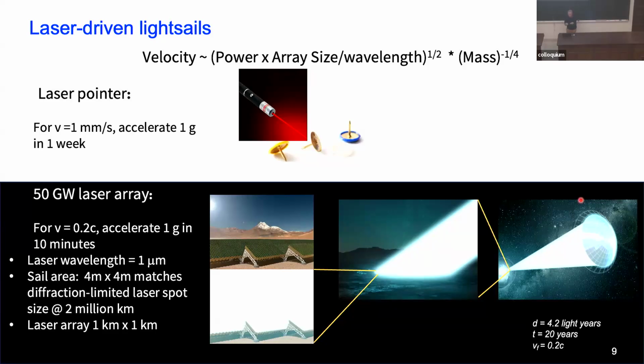So if we now apply the same governing relationship, at a megawatt per square centimeter for this 10 square meter sail, we would need about a 50 gigawatt laser array at a wavelength of 1 micron. We can talk about the choice of the wavelength if you like. And it requires quite a large laser aperture. That would be the largest laser system ever built. So this was a really exciting idea. When I first heard about it, I thought it was totally absurd.